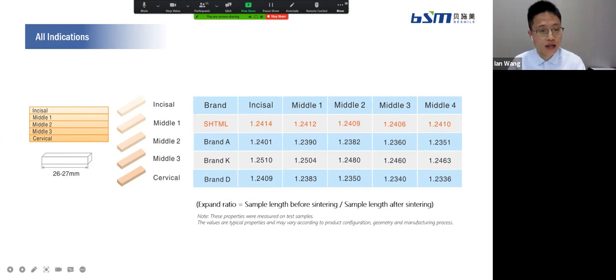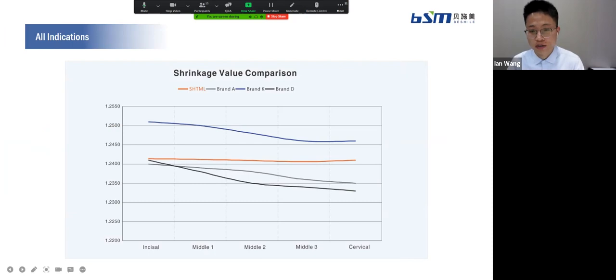So we did a shrinkage test. We made some samples from different heights of the blank, measured the length before sintering and after sintering, and then calculated the expansion ratio. And this is the result. Maybe in this chart, we cannot directly identify the difference, so we convert it to this picture. In this picture, we can see our SHTML has a very smooth line between the different layers, which shows the whole blank has a very uniform shrinkage. And we know that during sintering, the whole blank will get a uniform deformation.